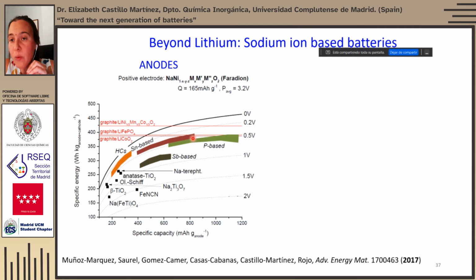as you can use an aluminum current collector in both electrodes instead of having to use the copper current collector that is in the lithium anode, because sodium as well as potassium do not form alloys with aluminum, and therefore you don't need to use copper. And aluminum is lighter than copper. Tin-based anodes and phosphorus-based anodes do have very large capacities because they are mostly based on the alloying reaction, and therefore they do have the issues related to pulverization and large volume expansion of the alloy materials. And hard carbons are actually the alternative that is being used in the initial commercial sodium-ion battery.